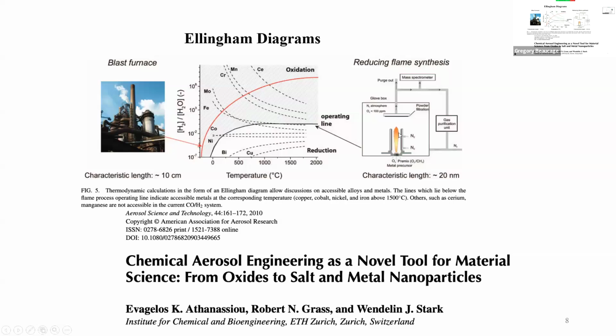So that's really severe quenching, getting really high concentrations formed all of a sudden. Then the particles form, so it's really far from equilibrium. So the particles that come out of this are going to be really small, like 10 nanometers, maybe 2 nanometers, really small particles, right? That's how people make particles, but a lot of times you don't want the oxide, you want the metal.